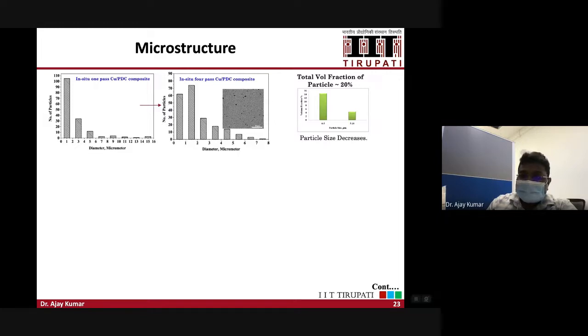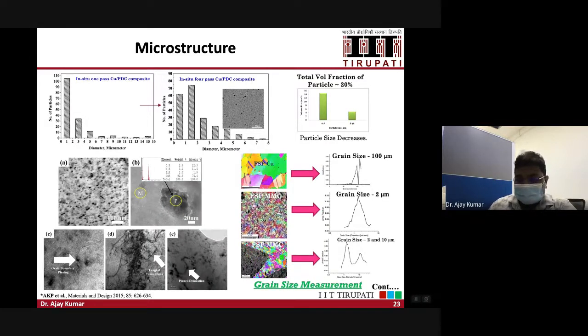Then we also calculated the volume fraction of the particles present in the matrix, and then we did the grain size measurement of the composite materials. So in the previous picture you saw that the annealed copper has around 400 micron, okay, and then here this is the copper. So here we have 100 micron. When you have the FSP of the copper materials, MMCs, here you have 2 microns, okay, and in this you can see 2 micron as well as 10 micron, okay. So you can see from 400 to 100 to 2 micron. So you are getting refinement of the grains during the process.